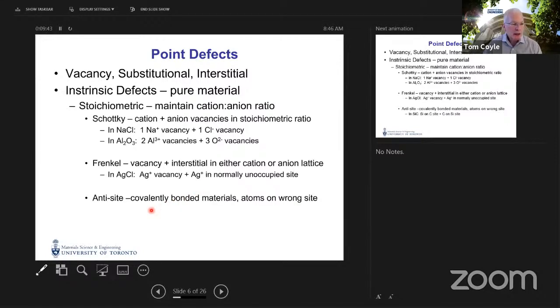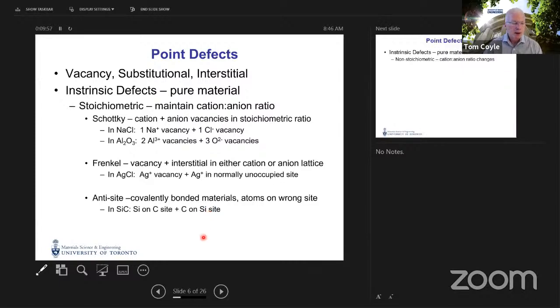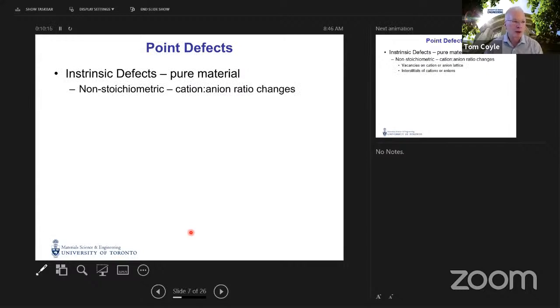Not important in oxides, but just to be complete, a third type of intrinsic defect is known as an anti-site defect. This is where in a material like silicon carbide, for example, the silicon would be found on a site normally occupied by a carbon, and the carbon would be found on the silicon site. So not important for oxides or ionically bonded solids in general, but to be complete, that makes the third type of stoichiometric intrinsic defect.